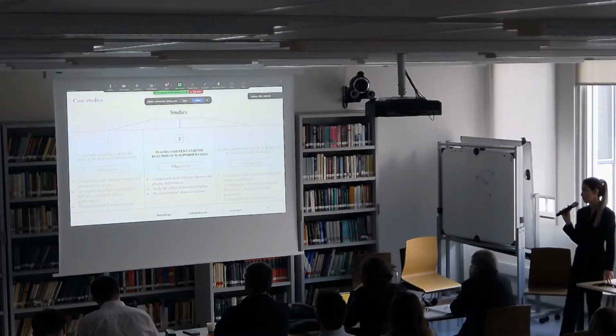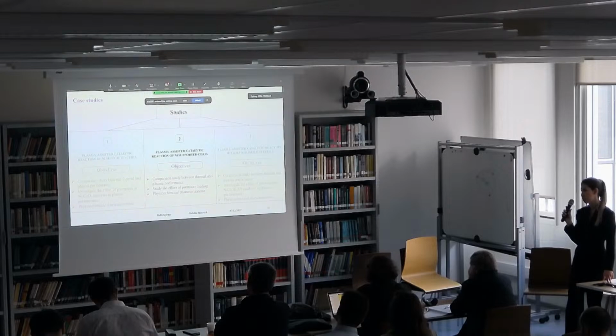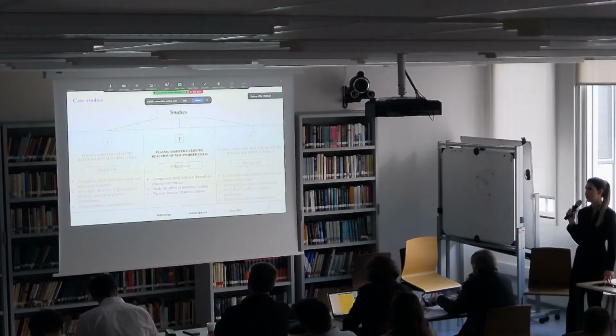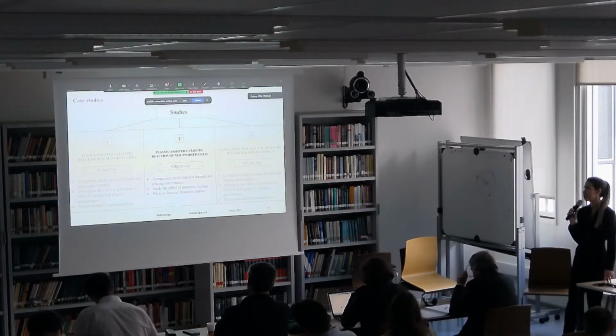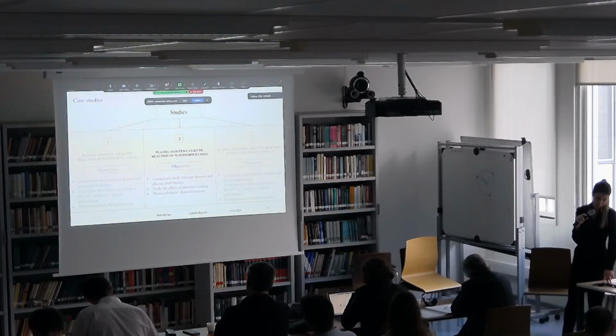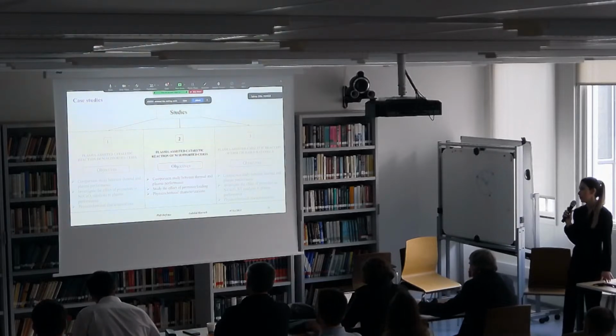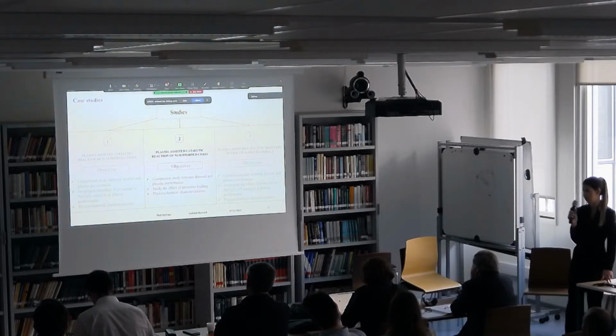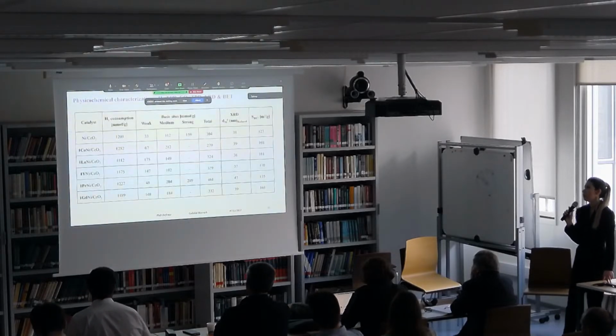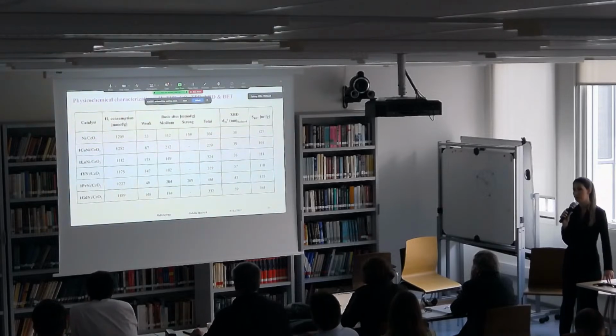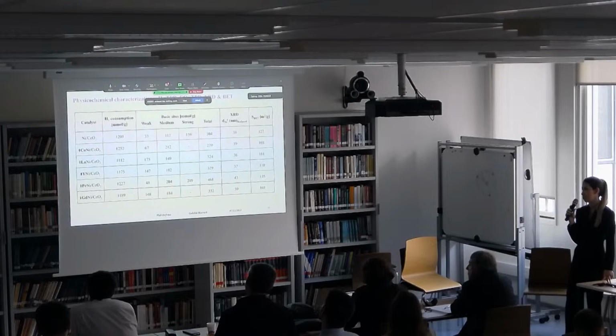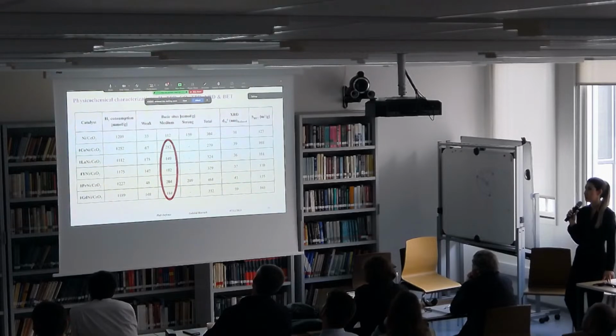So moving to the second part, we already saw that these promoters with this amount of loading did not really affect the catalytic performance. Based on the literature studies, if you decrease the amount of loading, the catalytic performance will improve significantly. So let's take a look if this really can happen under either thermal or plasma conditions. I did the same characterization on this series of catalysts. Just to summarize everything, I gathered all the information in one slide. As you can see, by decreasing the amount of promoter, the medium basic site amount increased significantly, which can already be expected from this series of promoters to improve the catalytic performance.